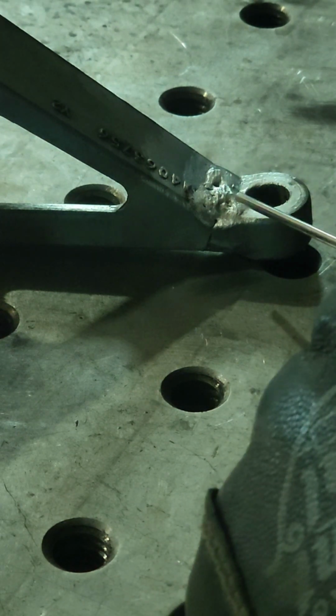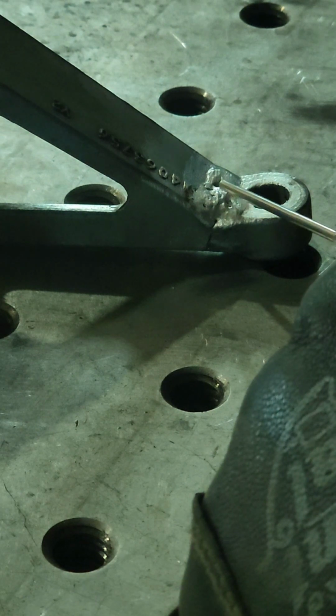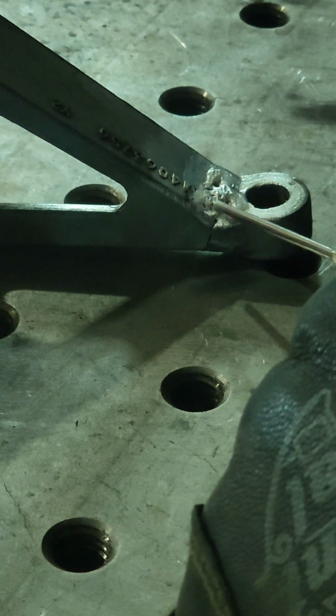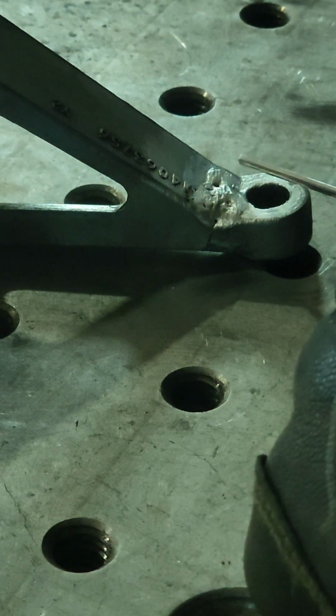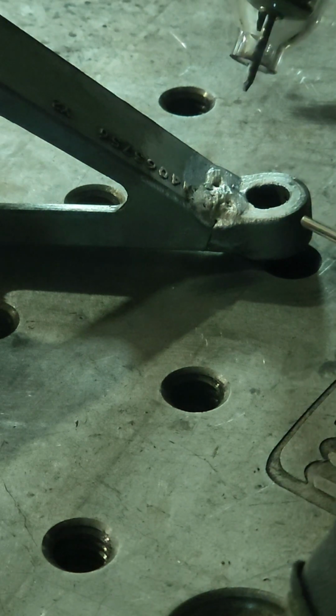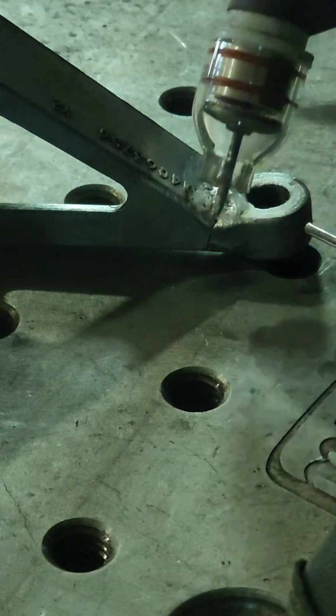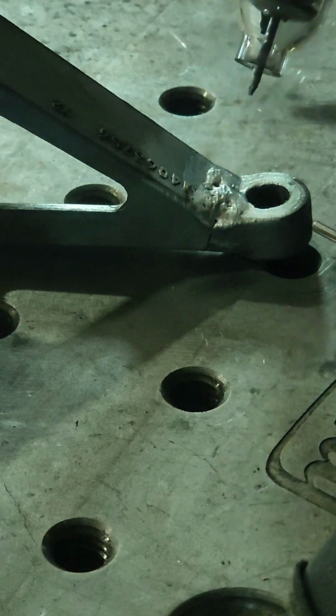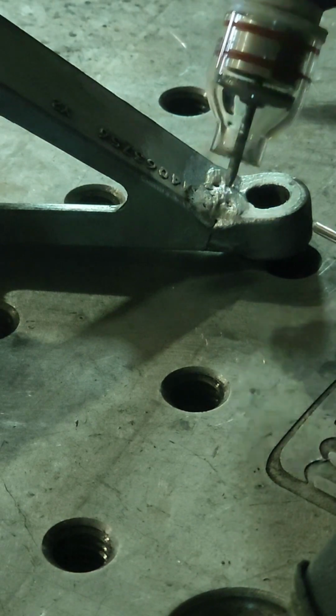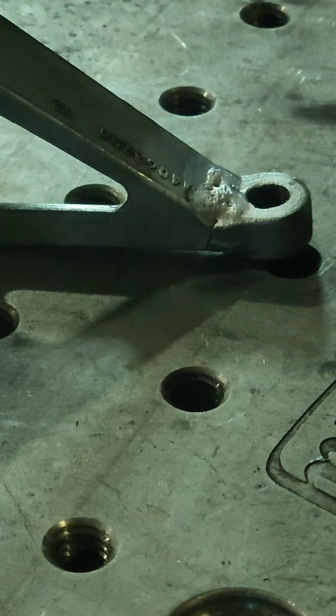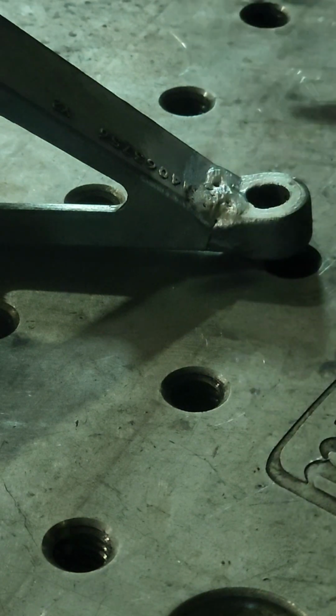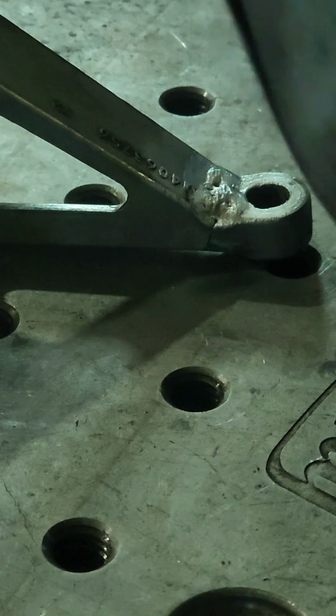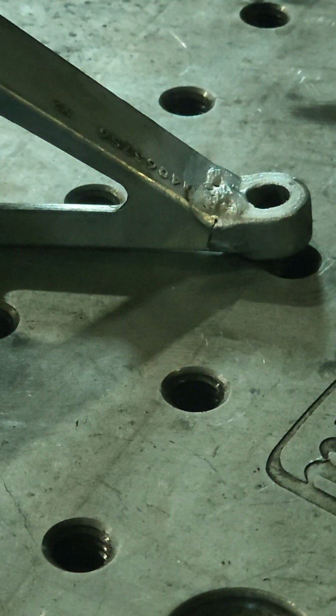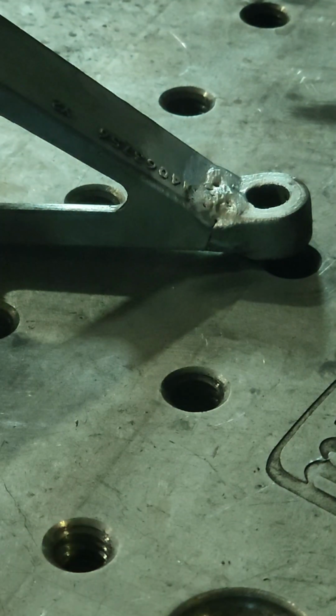So I cleaned it up with a little more acetone and wire wheeled it again. What I'm going to do is start back over here and just go over it with my cleaning action. I'm not going to wet it out to a puddle. I'm just going to go over it with my cleaning action a few times. And that's what that white frost is that you see. That's your cleaning action, your DC positive as it's switching back and forth on AC.